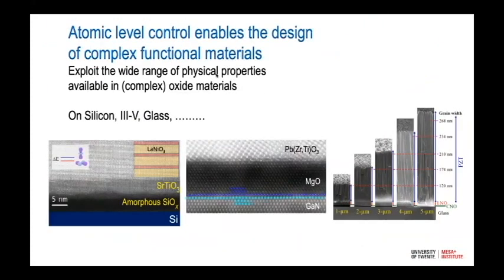And again, to just show a few examples. We have this atomic control also on this scale. So we can grow also now, and again, these are cross-section electron microscopy images, we are able to control the growth of these perovskite oxides on top of silicon even, and we have perfect epitaxial growth. For instance, on gallium nitride, so on III-V semiconductors, you can see magnesium oxide and a high dielectric PZT compound epitaxially grown on top of that.